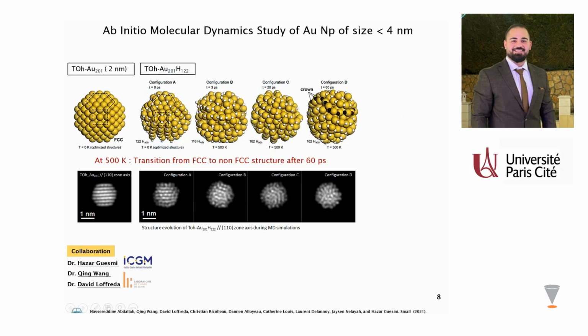So to understand the atomic origin of this structural transition of the gold nanoparticle, we followed, by ab initio molecular dynamics study, a gold nanoparticle having the same size of 2 nanometers, initially in vacuum, and then when covered by one monolayer of hydrogen, between 0 K and 500 K.